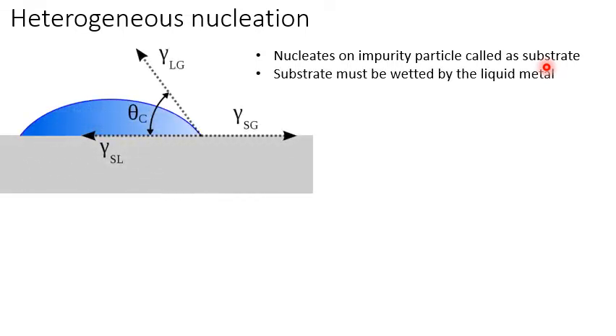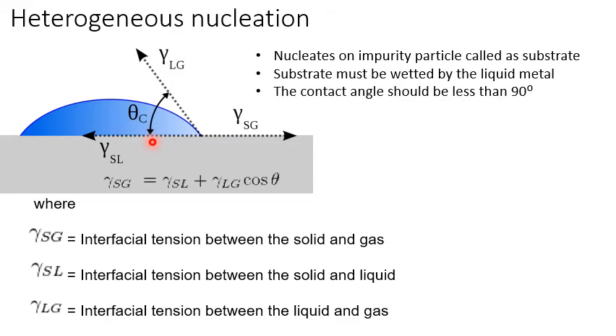Whenever a liquid droplet adheres to an impurity or the surface of the mold, theta c is the contact angle, where L stands for liquid, G for gaseous, and S for solid. Gamma SL is the surface or boundary which separates the liquid from the solid, and likewise for solid with respect to gas, and liquid with respect to gas. The contact angle should be less than 90 degrees. These are the interfacial tensions between solid, liquid, and gaseous phases.